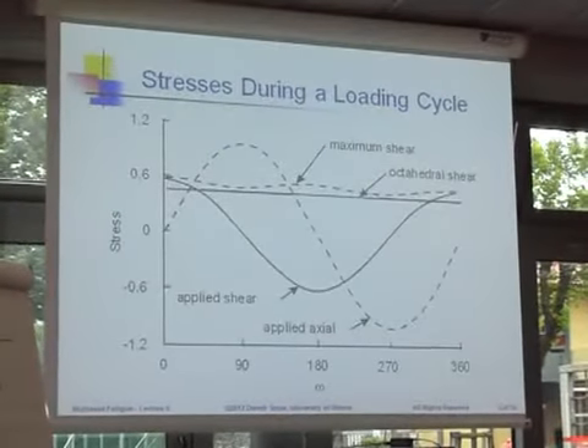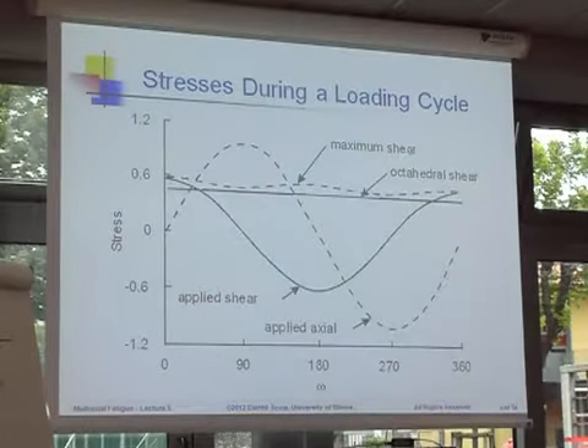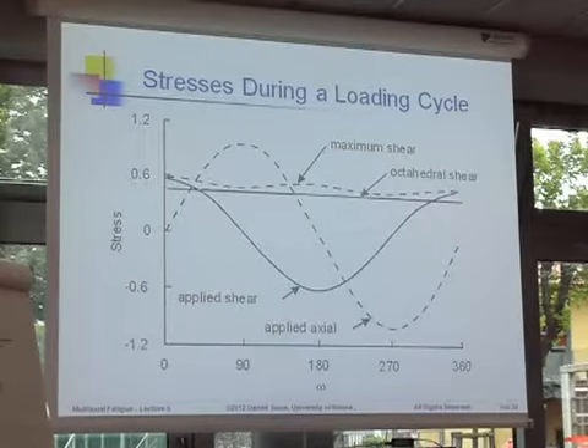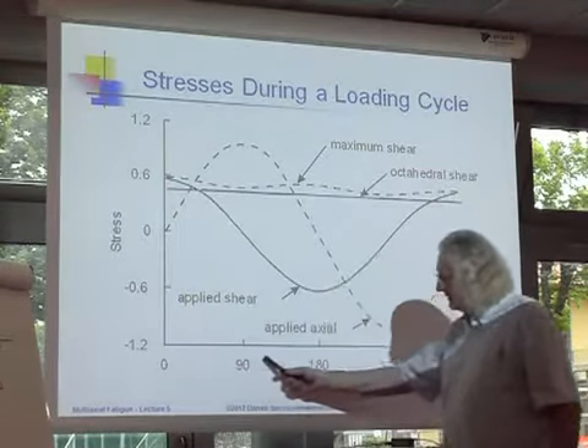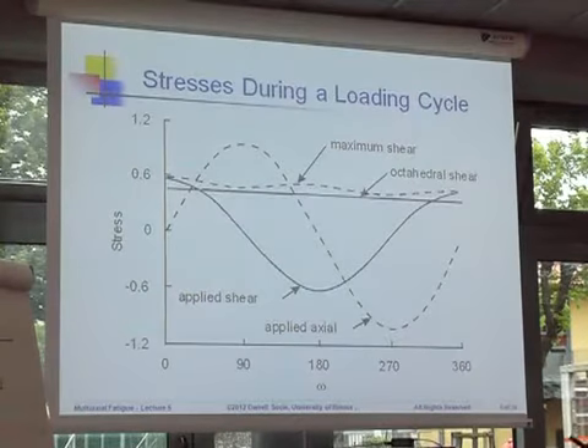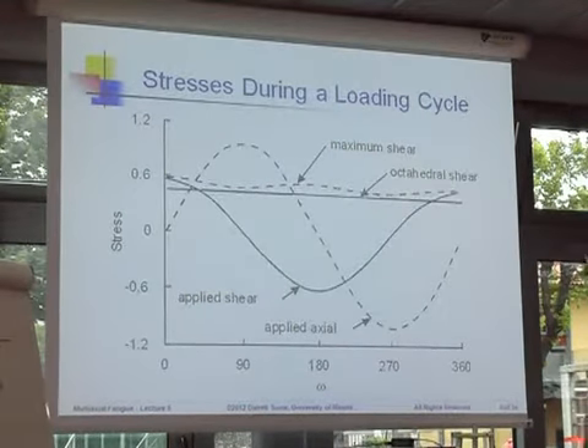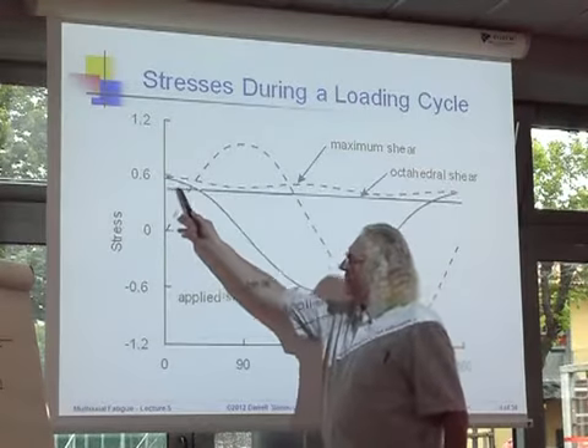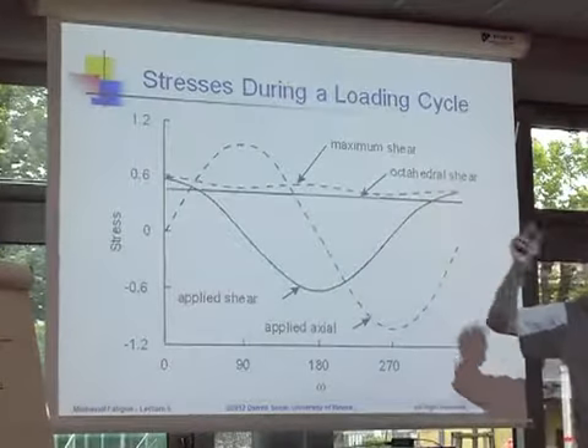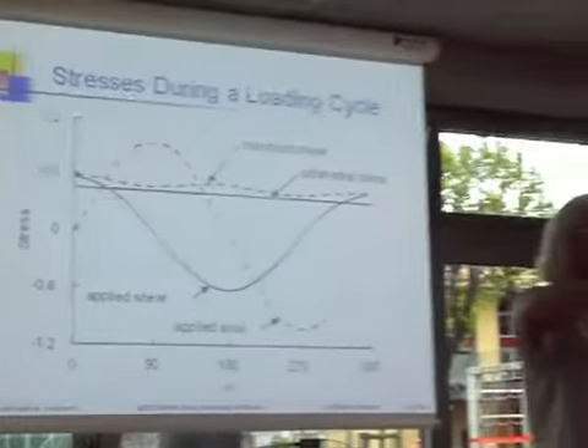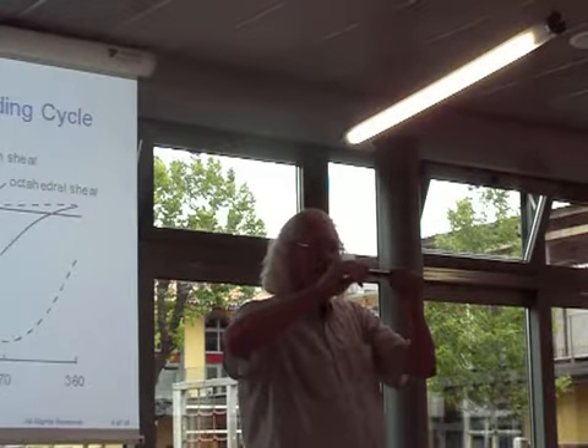So let's look at what happens in an out-of-phase loading test. The first thing is if we look at the stresses as a function of time, and here is a complete cycle, one loading cycle. If we look at the octahedral shear stress, then throughout the loading history, the octahedral shear stress is constant. So if I used something like Sines criteria for the octahedral shear stress with out-of-phase loading, it would always predict no fatigue damage, because the octahedral shear stress never changes. That's the purpose of the out-of-phase loading, right? So that's probably not a good criterion.